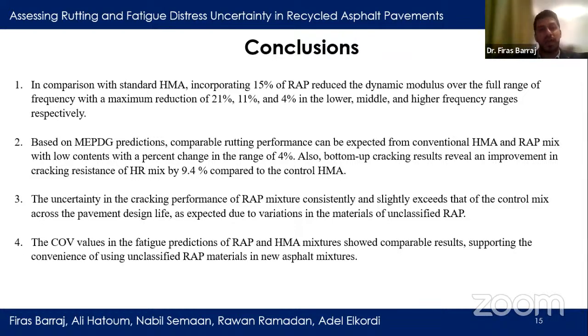Now, secondly, based on MEPDG predictions, comparable rutting performance can be expected from conventional HMA and RAP mixes with low content of RAP, with a percentage change in the range of 4%. Also, bottom-up cracking results reveal an improvement in cracking resistance of RAP mixes by 9.4% compared to standard HMA.